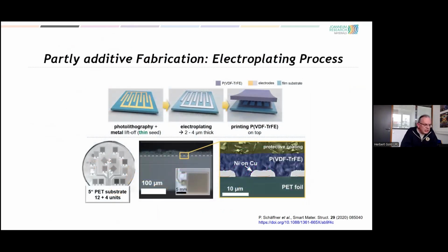transistor electrodes. But here would be a sort of semi-additive fabrication by an electroplating process. It would start by a subtractive process by photolitho and lift off of a very thin seed layer that just needs to be conductive. And then the thick layer would be added by electroplating, which could be regarded as additive, and then the PVDF would be printed on top. So this is semi-additive. This is good, but not good enough for our project with its radical approach.